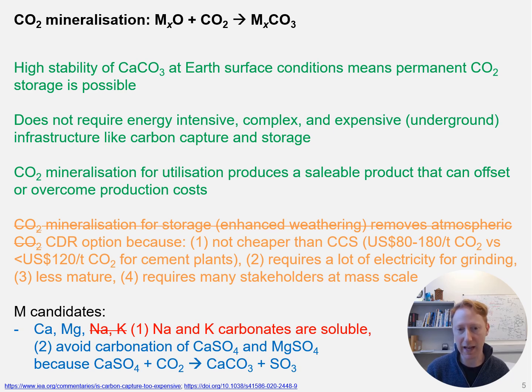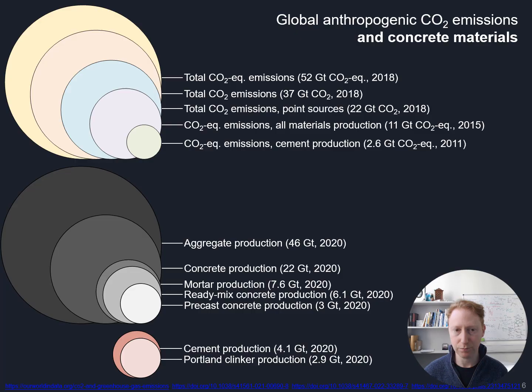In terms of the candidate elements for CO₂ mineralization, sodium and potassium are not good candidates since sodium and potassium carbonates are soluble. Calcium and magnesium carbonates, on the other hand, are good candidates since their carbonates are stable at Earth's surface conditions, but we just need to take care in general to avoid carbonation of calcium and magnesium sulfates, since this would result in undesirable sulfate emissions.